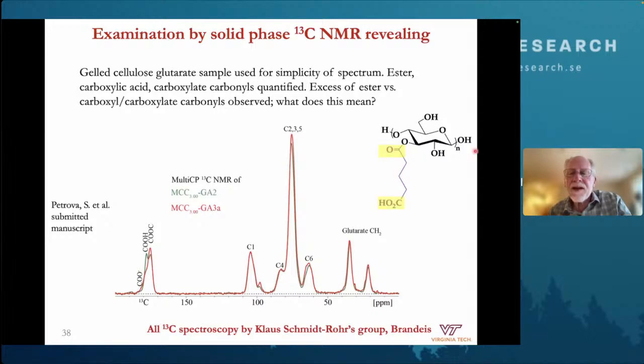We were able, fortunately, to work with a great group at Brandeis University on solid phase C13 examination of these hydrogels. This is a solid phase C13 spectrum. The quality of these things has gotten a lot better in recent years, and it gave us a tremendous amount of information. One thing it told us was that cellulose glutarates should have the same number of carboxyl carbonyls and ester carbonyls, but there was an excess of ester over carboxyls in this spectrum.